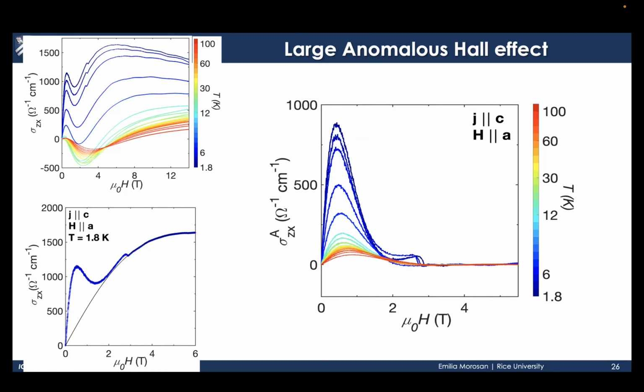And so when we subtract that normal Hall estimate, what we end up with is this manifold over here, the conductivity as a function of field for different temperatures, where there's a large peak centered more or less around 1 Tesla, and that persists, like I said, from the lowest temperature here, 1.8, all the way to 100 Kelvin, which is way above the magnetic ordering, right?